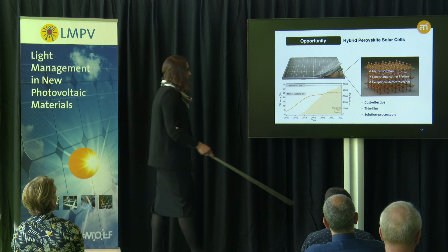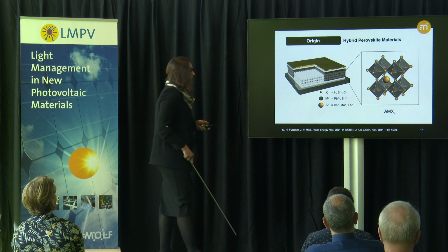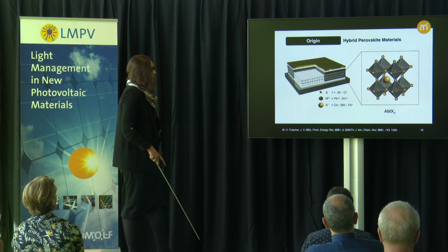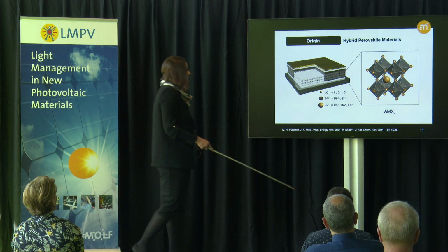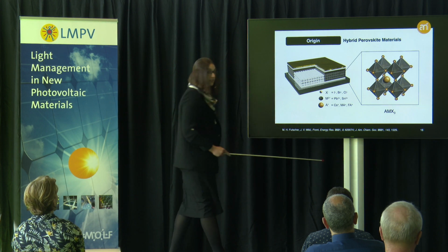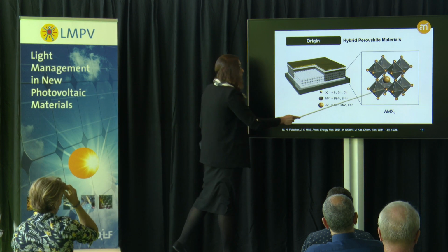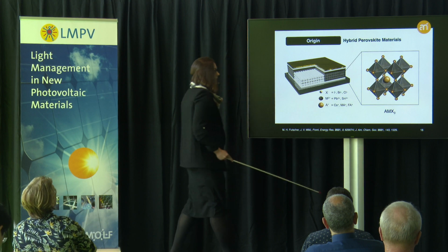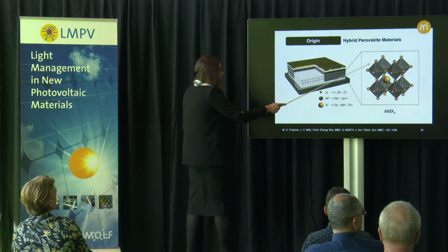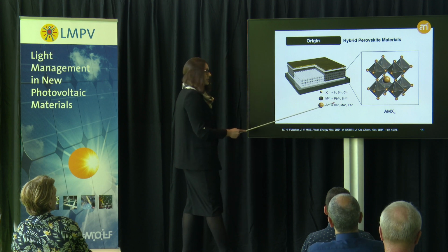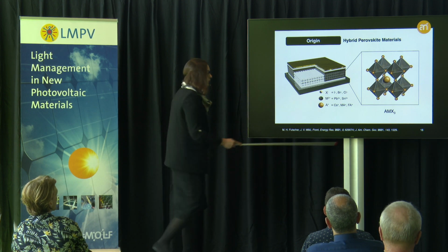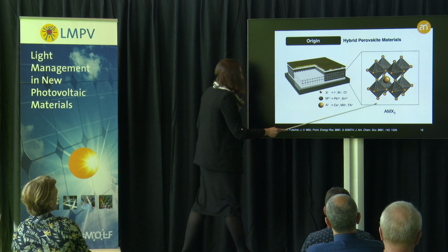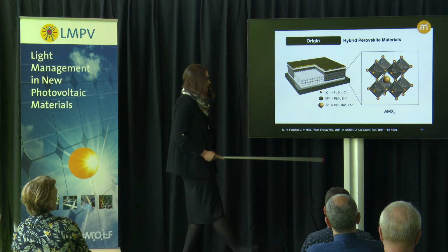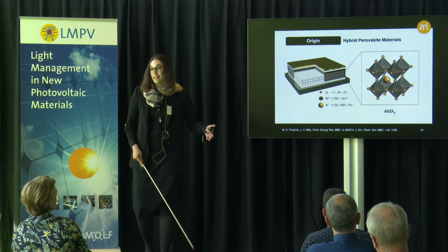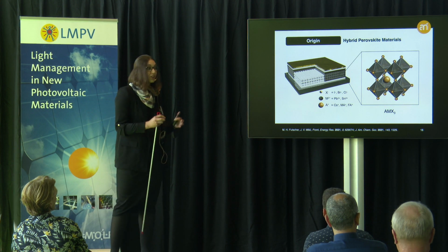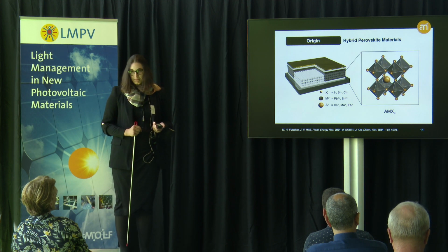Now, they're here illustrated by their crystal structure that is commonly defined, now diving deeper into the material characteristics, by this cubic crystal structure defined by the AMX3 formula, typically referring to this corner sharing octahedral framework that is defined by this metal halide containing the species primarily lead and tin and different halide anions, while hosting in this central cuboctahedral cavity A cations that can be either inorganic species like cesium or small organic molecules such as methylammonium or formamidinium, which really render these systems hybrid organic-inorganic materials.